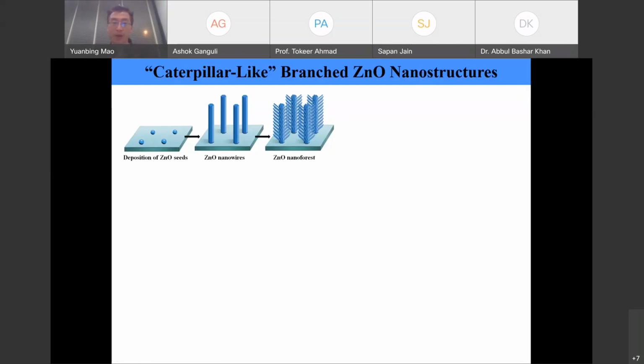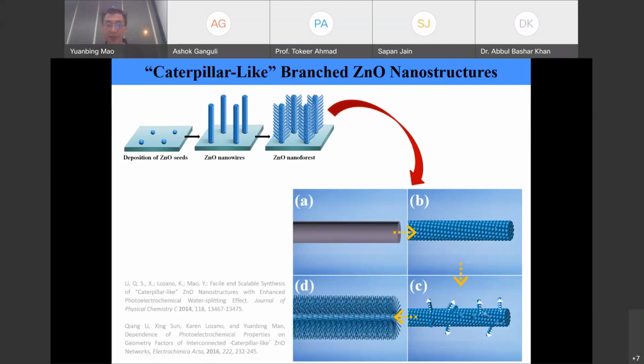These nanostructures are growing upward, so we've been thinking that maybe there is a better way to do that, right? For example, if I can make some zinc oxide nanofibers and convert them to zinc oxide nanoparticles, then we can use those nanoparticles as seeds. Then we can grow branches on these zinc oxide nanofibers, and based on the parameters we tuned, in terms of the PEI concentration and ammonia concentration, we can adjust the diameter and the length of those zinc oxide branches. So yeah, it looks interesting, right? So how do we get these zinc oxide fibers?